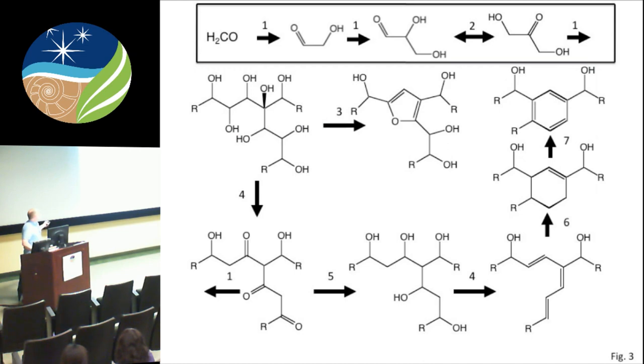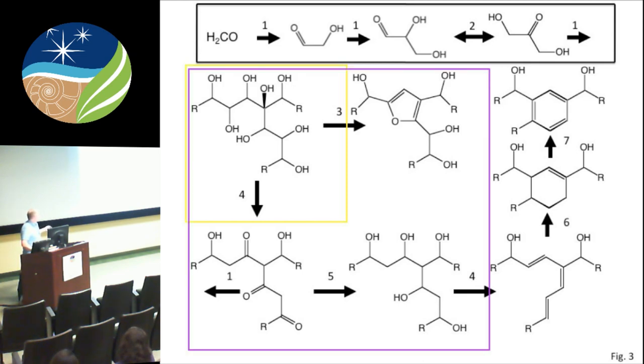He said, wait a second, we've got furans in our NMR. Our XANES are saying we've seen degradation of sugars. And so it suggested to me that maybe everything that we're seeing was linked through the polymerization of formaldehyde. The scheme here is that formaldehyde is about the simplest way you can imagine of getting a complex sugar, in a sequential series of what we call aldol condensations. You can make your way here. This sort of structure is representative of the most primitive of the stardust particles we've analyzed. Now here's furan, very abundant in our C13 NMR, and so this gets us out to the more processed, if you will, stardust particles.